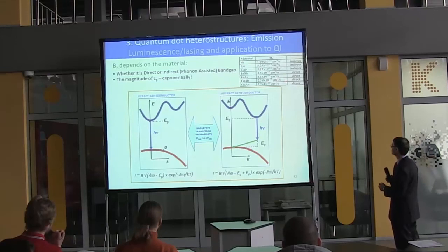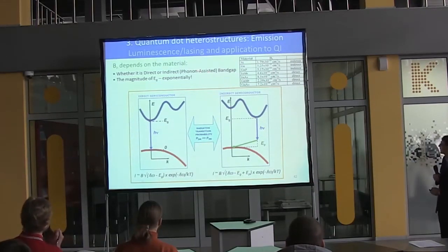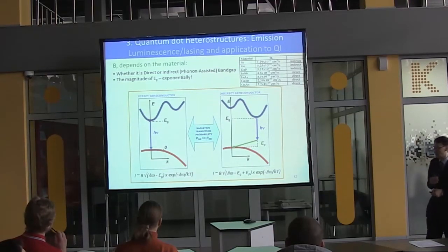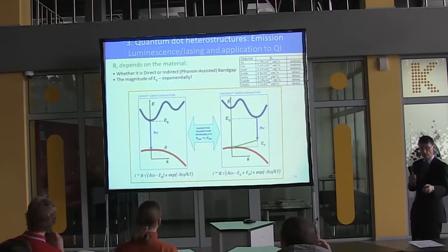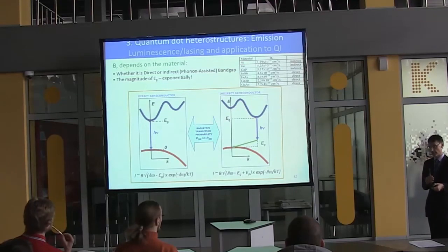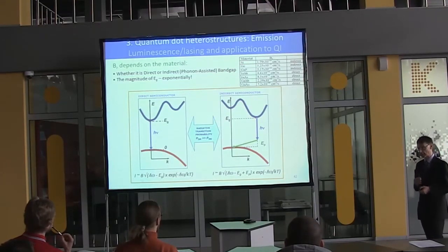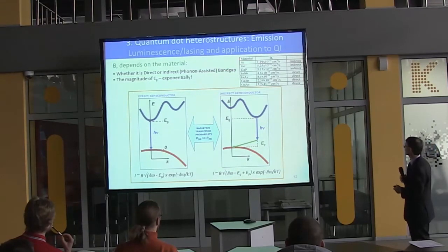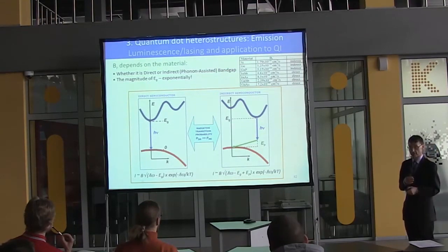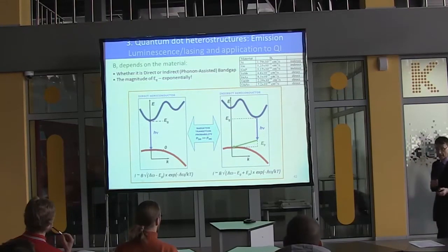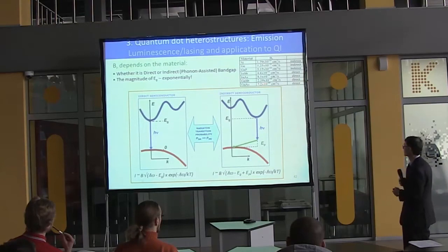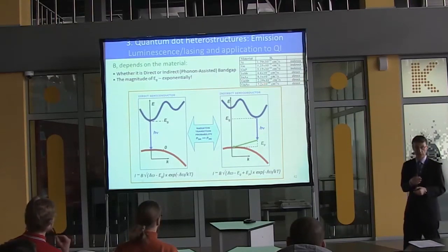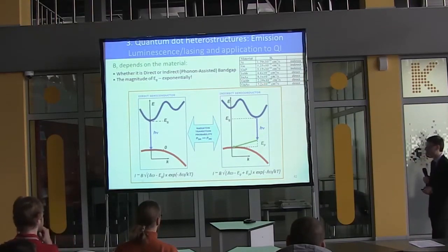And if I look here, you see 10 to the minus 14 or 15 for these chaps at the top. If I look at the direct gap ones, 10 to the minus 10, 10 to the minus 11. So what have I got? 4 or 5 orders of magnitude difference in the chance of getting light out of an indirect gap semiconductor compared to direct. So if I want to take silicon and make a laser, what's the answer? Don't bother, right? And that's why no one's done it. You don't make semiconductor lasers from these materials. And people have tried doing all sorts of clever stuff, but you're really fighting nature, okay?